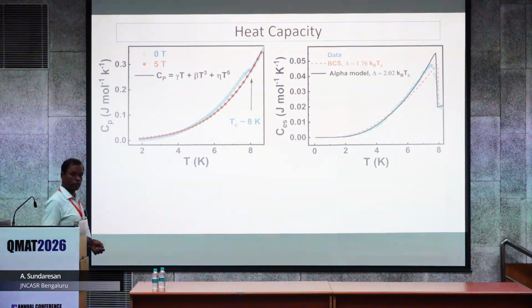Then we move on to the heat capacity. This is the heat capacity at 0 field and then 5 Tesla. When you apply 5 Tesla field, you can fit with gamma T plus beta T cube and phonon contributions, and it fits quite well. We can estimate the electronic contributions by subtracting the phonon contribution.